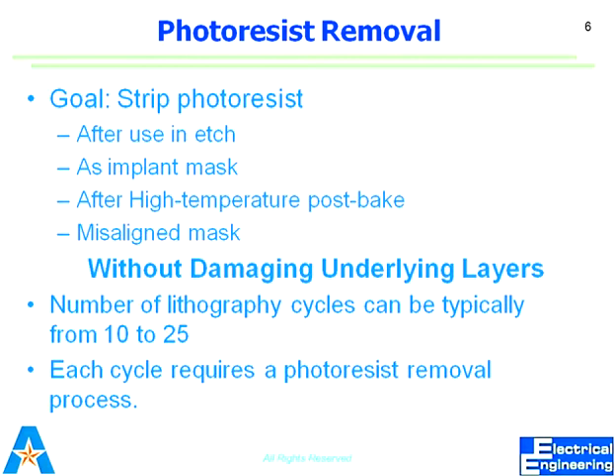It means that the limitation is that the metallic layer that can be patterned in this case will be very thin only. If it's going to be thick enough, in that case, it will become a blanket type deposition. So then even the removal of photoresist will not lift the thick layer of metallic layer up. So if it's thin, there would be a breakage or not a strong bonding between the pattern that we want and the pattern that we remove. So if there is a height difference, this layer, they are not connected, so that would be removed.